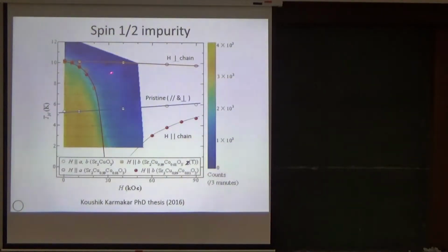So this is how the phase diagram looks. When the field is applied perpendicular to the chain, the Tn is gradually decreasing. When the field is applied parallel to the chain, this is what the behavior is like. The transition temperature first decreases and goes below our measurement temperature limit, and then a new phase transition appears, and in this phase the transition temperature increases. And this is for the pristine chain, both parallel to the chain and perpendicular to the chain, we see the same behavior.